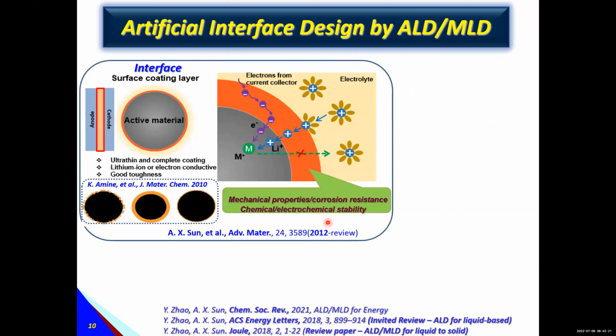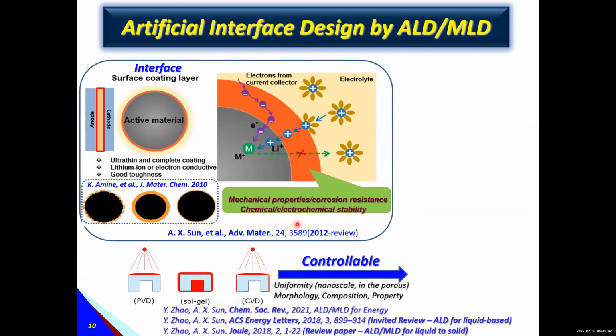So let's talk about the interface. We know an artificial interface is a good approach. What is an ideal interface? We need an ultra-thin, uniform interface. At that interface, we want to control different properties, for example ionic conductivity, electronic conductivity, and even mechanical properties like toughness. So different groups work on different approaches to make an artificial interface, for example CVD, PVD, or solution methods. But none of them can get ultra-uniform at the nanoscale. ALD and MLD are good approaches to get a nanoscale, ultra-uniform artificial interface.